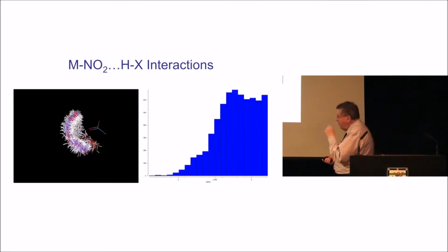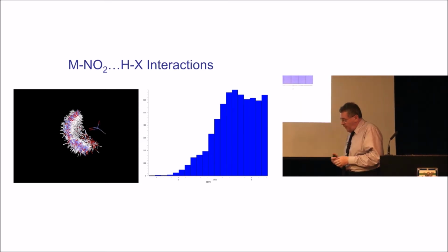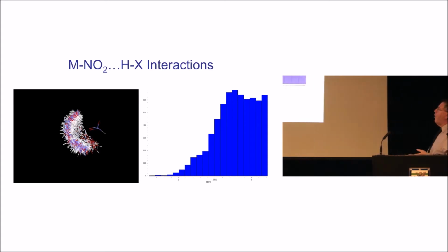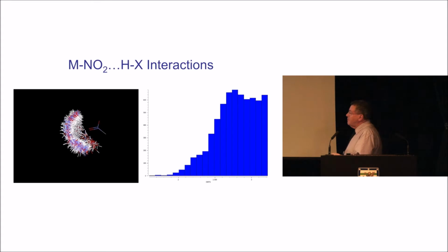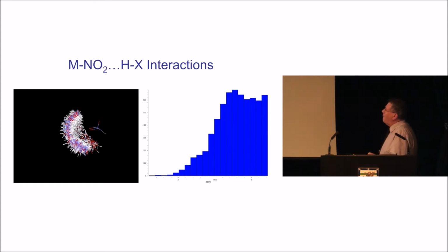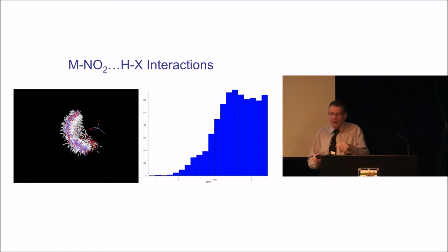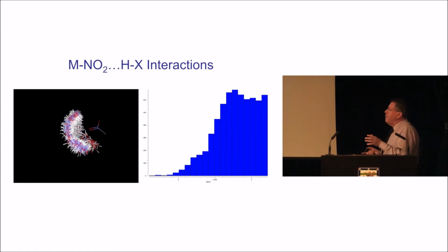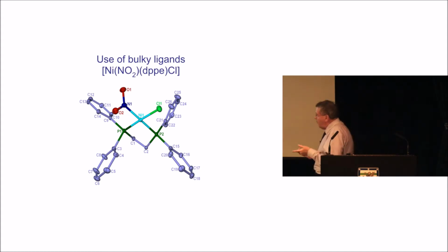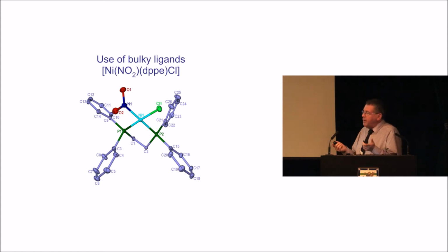And it's worth looking at the CSD for this. So here's the interaction for the NO2 group for all types of hydrogen bond interaction. And you can see that there's a range of distances. So it looks as if the energy map for this surface is actually fairly shallow. So maybe not too directional in terms of the interactions. But let's go back to looking at what sort of ligands might do it. So here we've got a nickel nitrosyl complex with a bulky phosphine. Well, the idea of introducing the bulky phosphine is to introduce the idea of this dominating the packing.